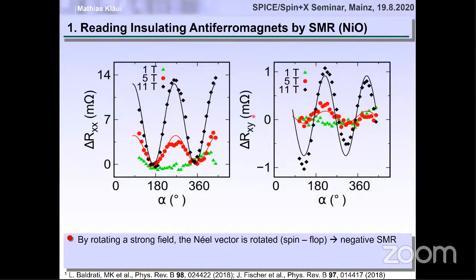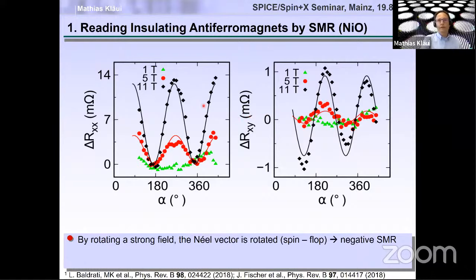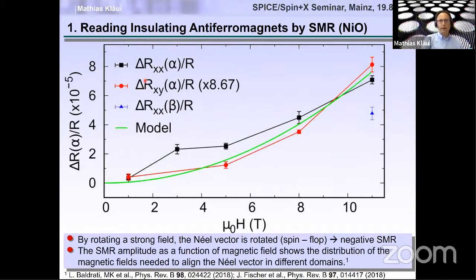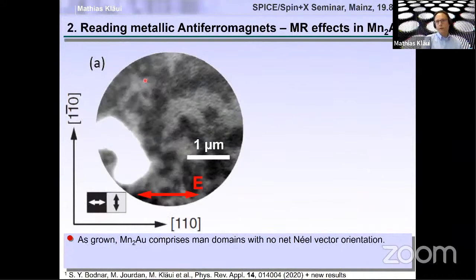longitudinal and transverse resistance. And you see that if you go from small fields to large fields, the amplitude of the signal gets larger, because at 11 Tesla, we can rotate more of the Néel vector than at 1 Tesla. And you can actually plot this and see there's a nice fit to a theory which was developed by Helen Gomonay explaining this. So SMR allows us to actually detect the direction of the Néel vector in the insulating antiferromagnets. So now if you have a metallic antiferromagnet, then you can actually use a different effect. So with a metallic antiferromagnet such as manganese two gold, we can firstly also do XMLD PEEM imaging, where we see here that we have as-grown domains, random domains, where the Néel vector is either pointing up or down. This is this light gray, or it's pointing left and right, which is the dark gray.